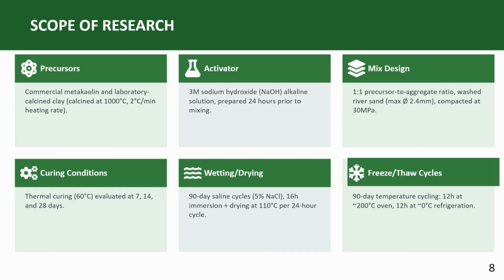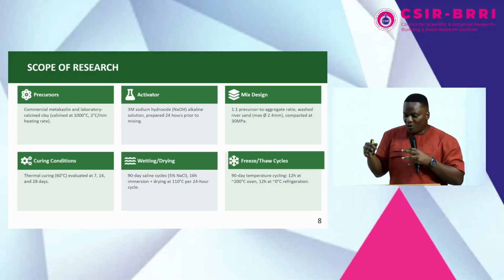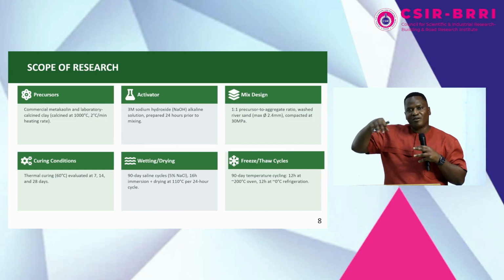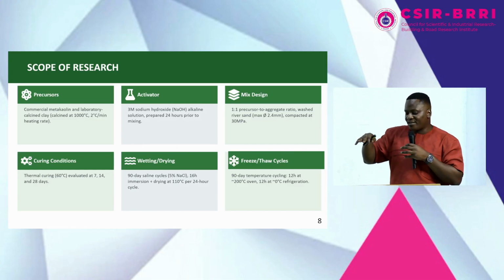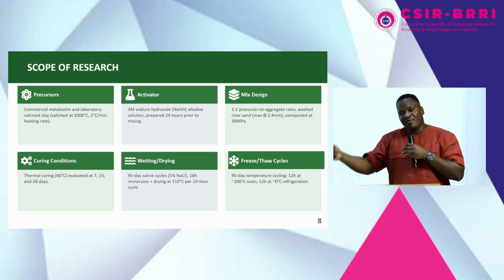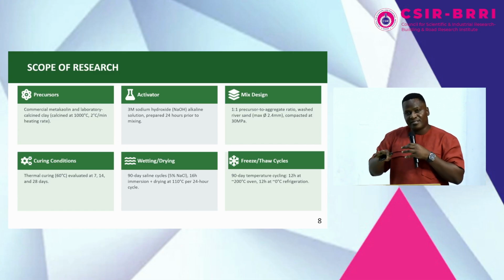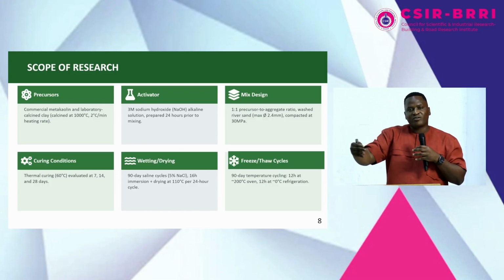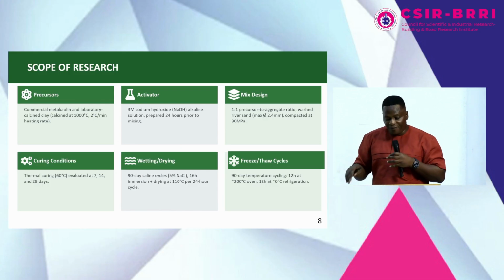And it was compacted under a load of 30 megapascal to give the two materials the same playing field, so that you'll be able to determine their porosity. Because if you don't compact them using the same mechanism, one may be more porous than the other. But if you subject them to the same treatment, whatever results you get, you know that you gave everybody a fair playing field.